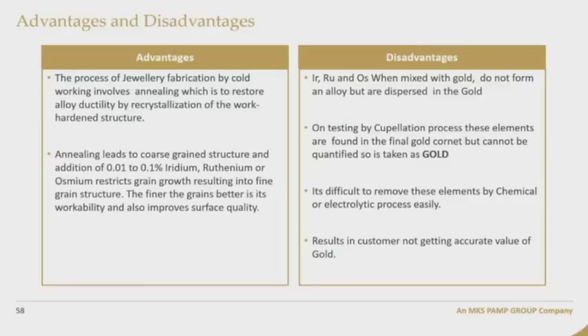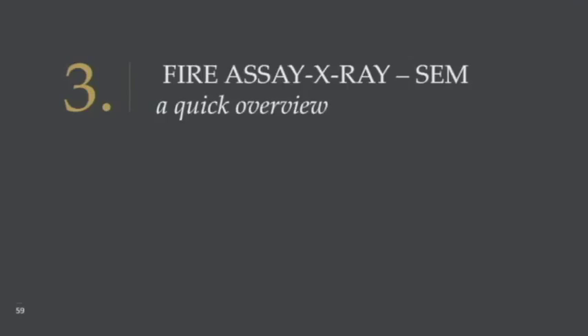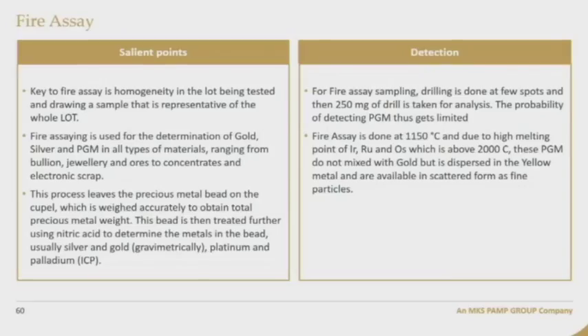The finer the grain, the better the workability, and it also improves the surface quality. A few disadvantages which have been prevalent: when mixed with gold, it doesn't go into solid solution and is dispersed in gold. On testing with the cupellation process, these elements are found in the final gold cornet and cannot be quantified, so it is taken as gold. It is difficult to remove these elements. I'm not saying it's impossible, but it's difficult to remove these elements by chemical or electrolytic process easily. So this results in the customer not getting the accurate value of gold. I would call Pankaj, who will explain the instruments we used for testing, and then I'll come back to you on the results which we achieved.